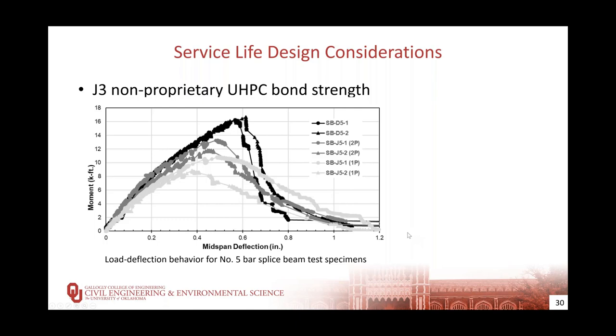All splice beam specimens exhibited similar load versus deflection behavior, especially early in the loading. It can be seen that the proprietary UHPC specimens with 2% steel fibers exhibited the highest loads and corresponding bond strengths. There was an increase in bond strength when the fiber percentage increased from 1% to 2% for the non-proprietary UHPC.